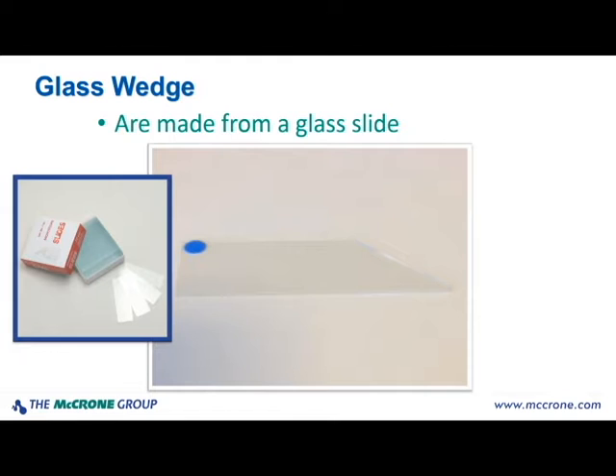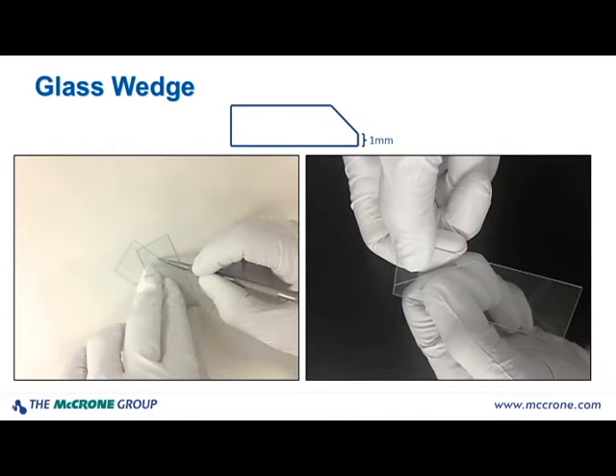The glass wedge method requires the use of a glass slide, and we turn it into what we call a wedge. And again, everyone has slides laying around, so you can make these yourself. You make the wedge by scoring the corner of a glass slide with a carbide scribe, leaving approximately a 1 millimeter foot on one end, and then snapping it off. You just want to make sure that when you do the snapping, you snap away from yourself, and be careful so you don't cut yourself.